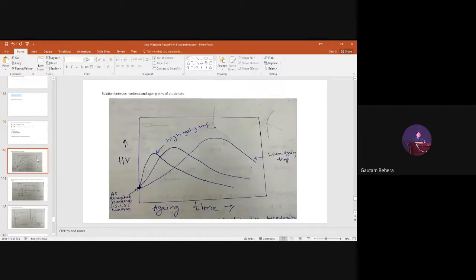And there is a very interesting figure over here. This is hardness, Vickers hardness HV, versus the time of aging. If you remember, aging means we allow the material to stay at a relatively low temperature so that precipitates will start forming. A precipitation will occur in the matrix phase. You can see these are very good, interesting plots. This is for low temperature. Sorry, this is for the high temperature plot, and this is for low temperature.